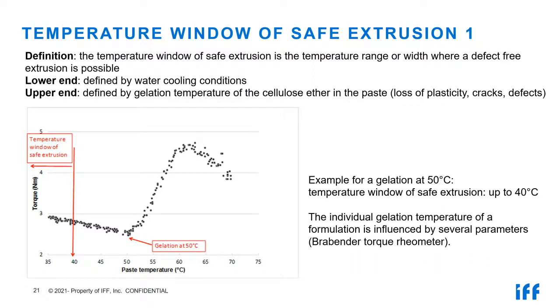One of them is the extruder in the lab normally is smaller than in the plant. If the extruder is large in the plant, of course the cooling conditions are worse compared to the lab, because the ratio between a cooling surface and processed material is very different from the lab, and normally it is a negative effect, which leads to an increase of temperature in the processed phase. This means you are coming closer to the gelation temperature compared to a similar trial in the lab.